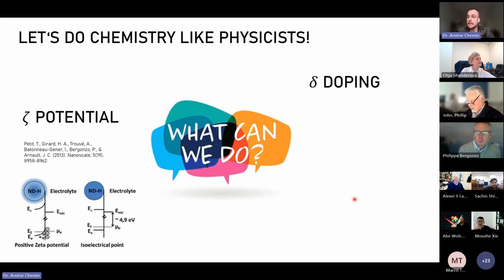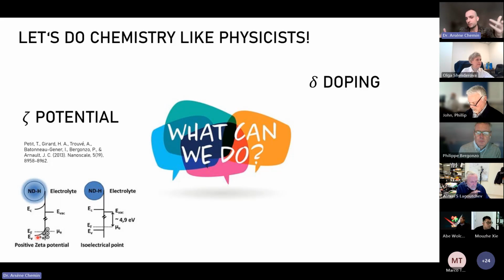What we can also understand is the zeta potential. So I told you about the work of Petit et al. They made a very nice description of the zeta potential using a very similar theoretical framework, where you have the equilibration between the Fermi level of the nanodiamond and the environment. The only little thing I could say is that in nanodiamonds, you actually cannot really consider band bending because the nanodiamonds are so small compared to the charge depletion layer, so they just charge overall. So you would have positively or negatively charged nanodiamonds.